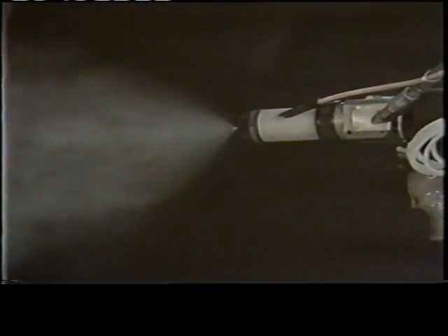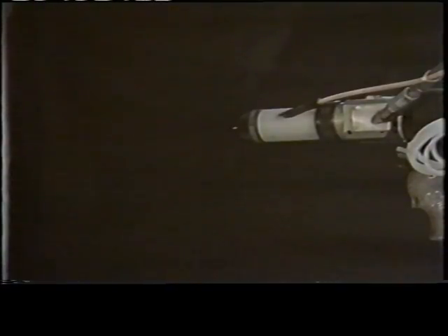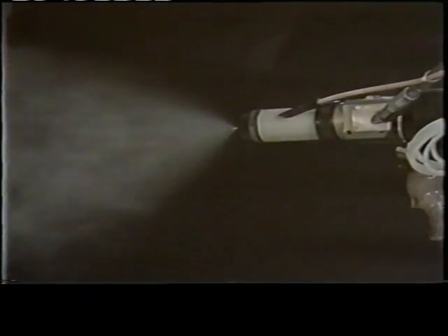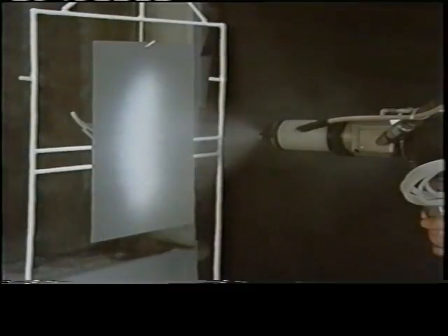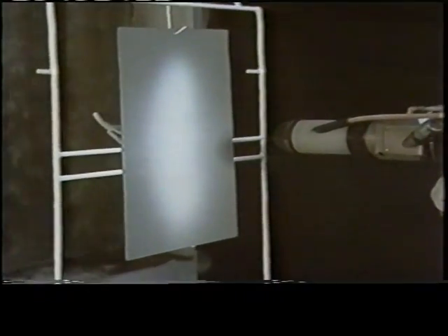The DeVilbiss equipment performed extremely well in the automatic line simulation. The coating went on very smoothly and evenly. There was no change in the spray pattern at the end of the test. This gun showed less coating buildup on its tip than any other piece of equipment evaluated.